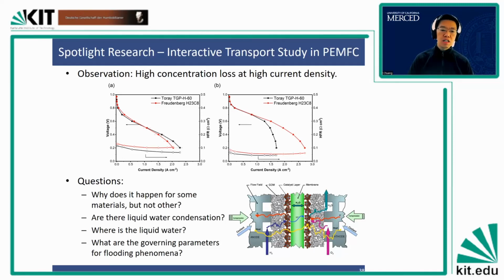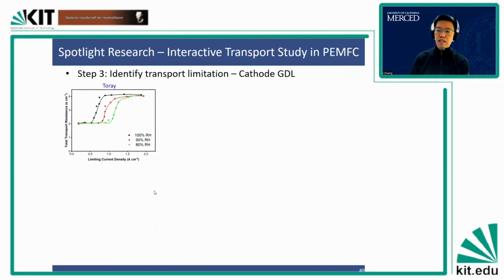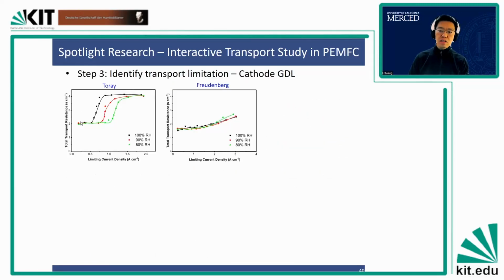But based on our study for the gas diffusion layer, not microporous layer, the performance is still relatively good. It degrades a little bit. When I say degradation, if you take a look at this chart, the onset of flooding and the level of flooding increased, but the trend still remains pretty good. Having said that, our ECSA loss and our membrane thinning are much more severe at that time. So that would be my experience. I don't know if there are other experts in this area who can comment on this.